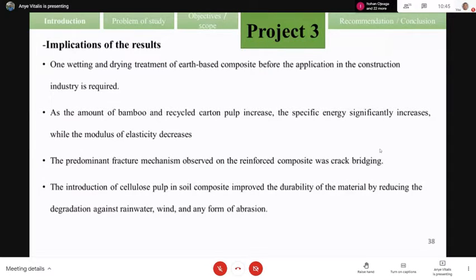We recommend using one cycle of wetting and drying as treatment of this earth-based material reinforced with cellulose fiber to improve the water absorption and the drying shrinkage, if we want to use this as a building material. Also, we recommend the cellulose fiber can help to improve the mechanical property of our earth-based material.